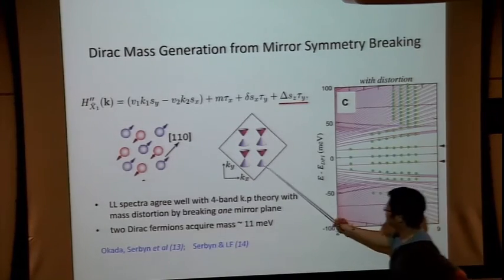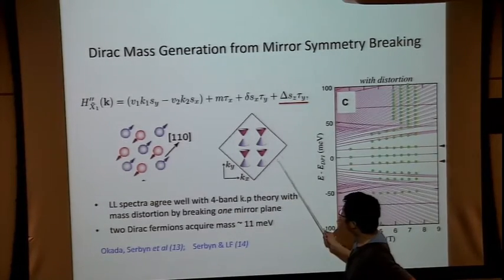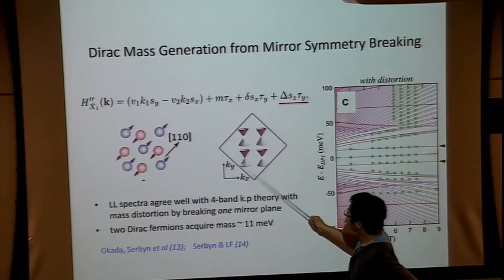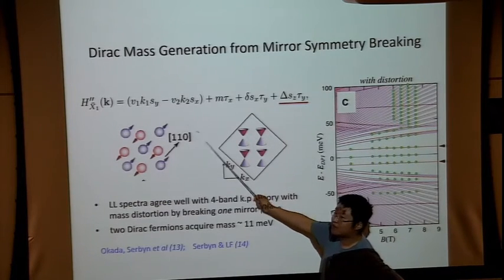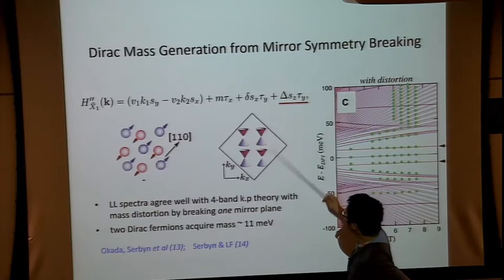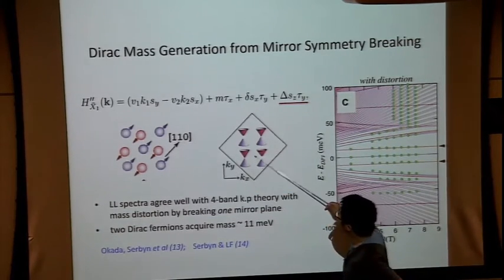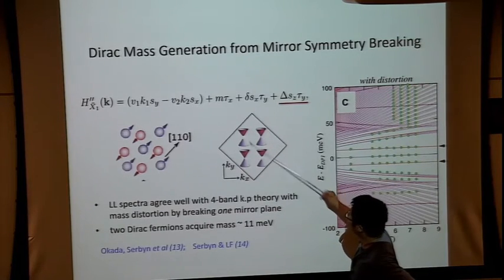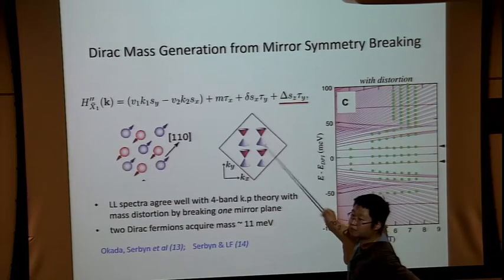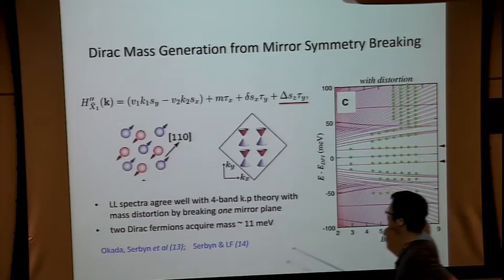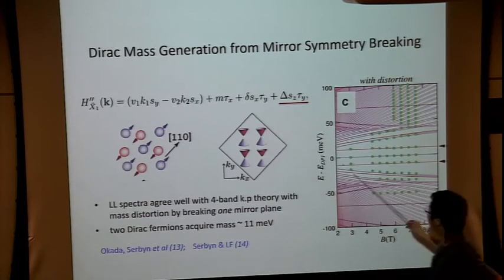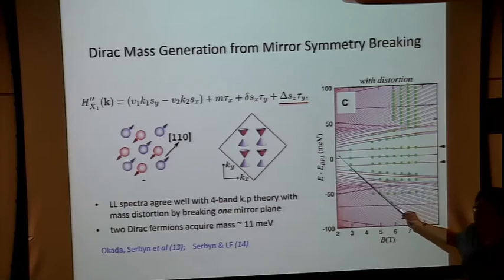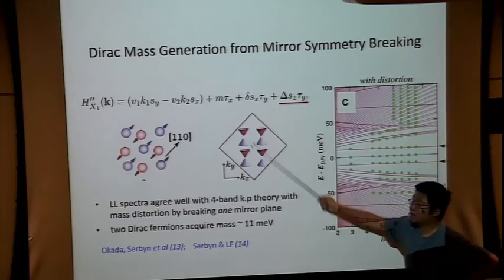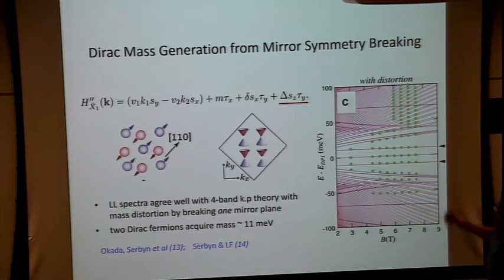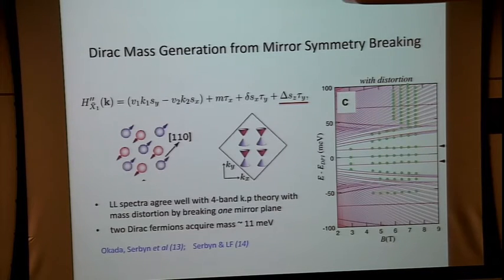So based on this experimental data, we infer that a distortion occurs along a particular mirror axis, 110, so that one mirror symmetry remains present. Along this mirror symmetry, two Dirac fermions remain massless, and the other two Dirac fermions are gapped with mass of opposite sign, that is guaranteed. So these two massless Dirac fermions give rise to two degenerate zero energy Landau levels in the middle, and these two massive Dirac fermions with opposite mass give rise to Landau levels on the sides.